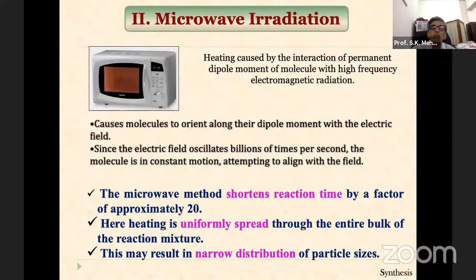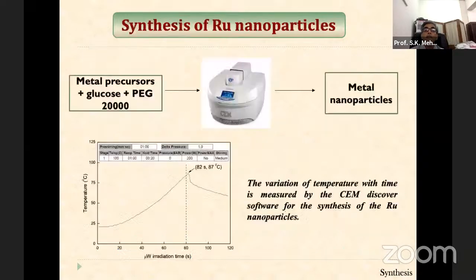The other is microwave irradiation. I need not tell you that the microwave method has become very famous because it shortened the reaction time by a factor of approximately 20. Heating is uniformly spread throughout the entire bulk of the reaction mixture, so there is no problem. This method is also very important because you can get a narrow distribution of particles. That is a very big advantage we have for this.